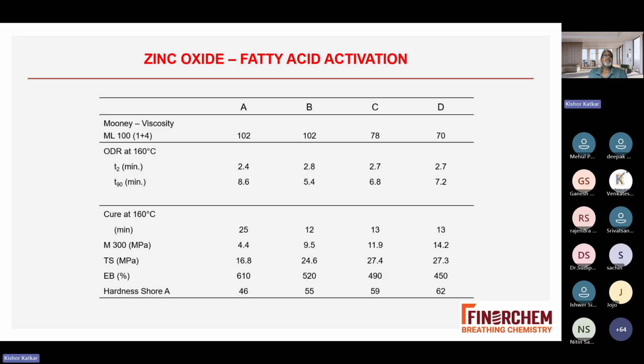So you can see the properties also. Now, A, B, C, D: A has no zinc oxide or stearic acid, B only zinc oxide, C less stearic acid, D the proper zinc oxide and stearic acid. What do you observe? You can see scorch safety is not bad, but T90 is affected. When there is no zinc oxide and stearic acid, it is the highest T90. As you have started using activator, your curing time is coming down.